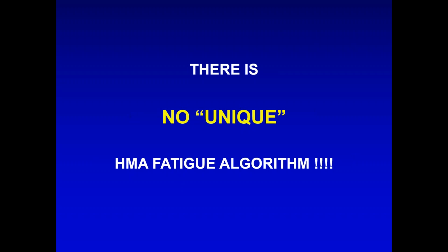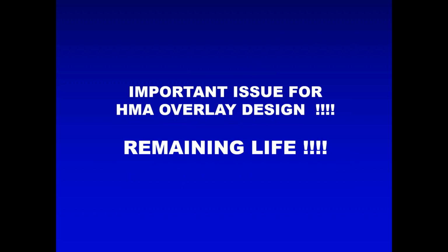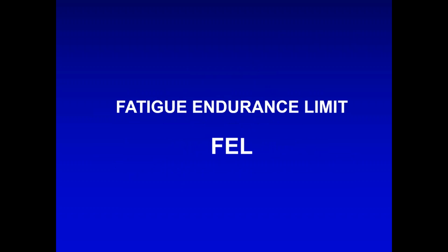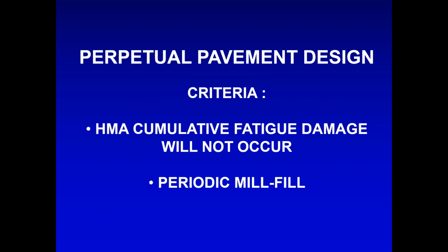There is no unique fatigue algorithm for hot mix. We can assign one and use it for design, but that doesn't really mean we'll have that particular mix in the field. Remaining life: how long do we have left in an old pavement section that we're rehabbing? That is a major issue, and it continues to be worked out. Fatigue endurance limit is that particular value of strain below which we don't get any damage. If that's the case in a perpetual pavement section where the fatigue endurance limit is controlling, we just periodically mill and fill the surface and we're home free.